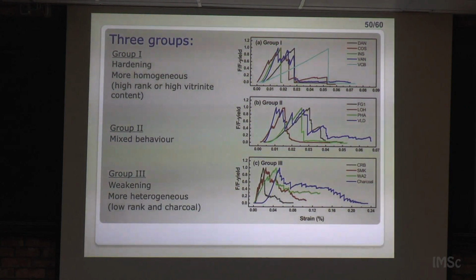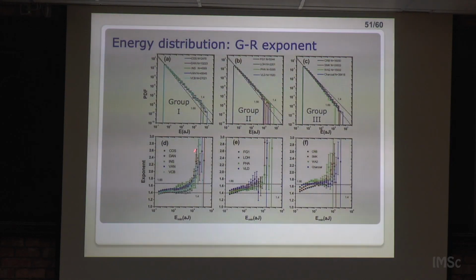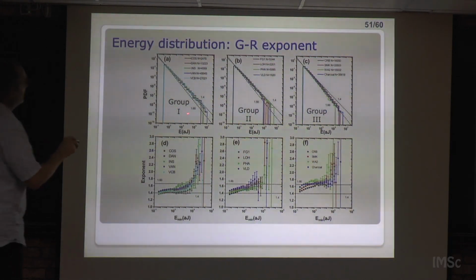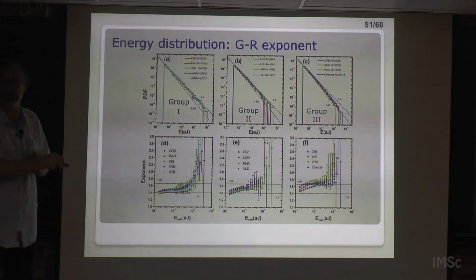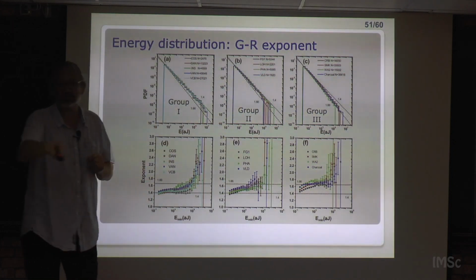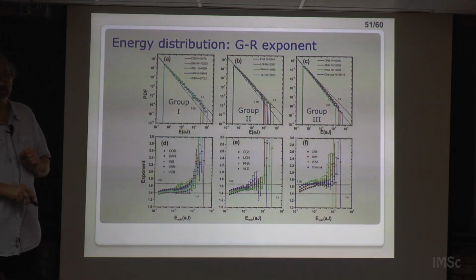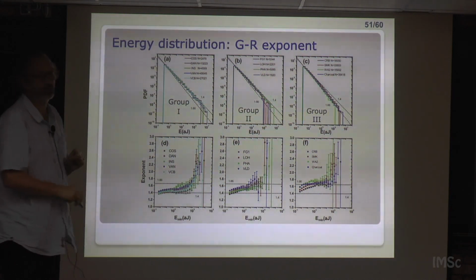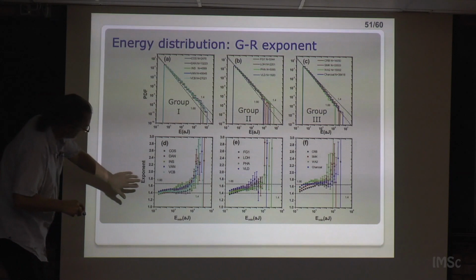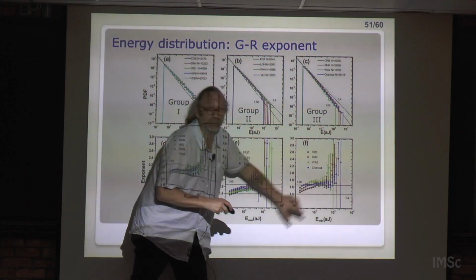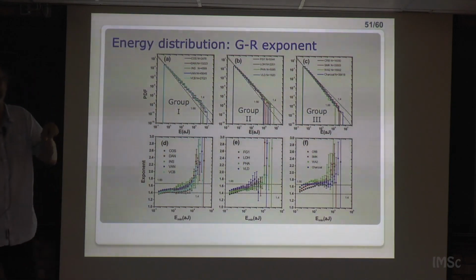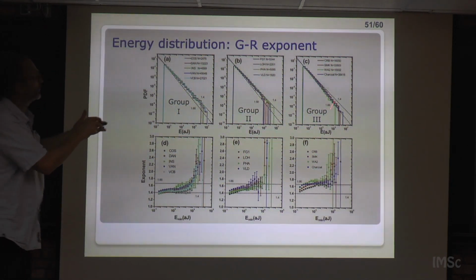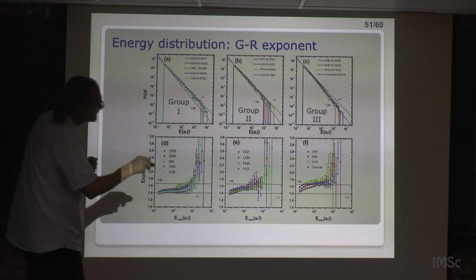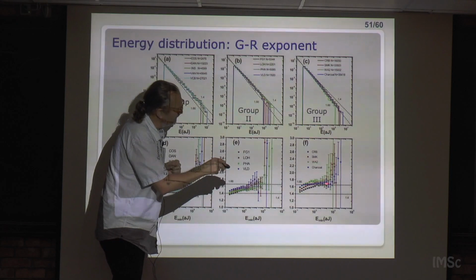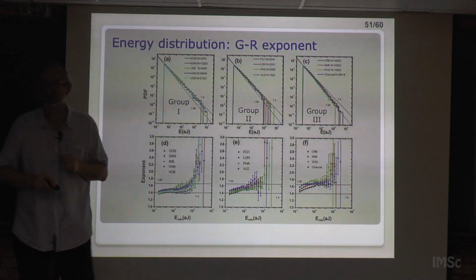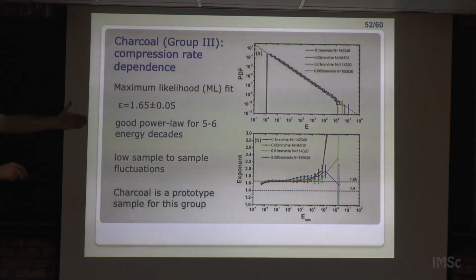And then we do the analysis of the two groups, and we compare. What do we find? The Gutenberg-Richter exponent, maybe you cannot see it here, but forget group 2. For group 1 it is 1.4. For group 3 it is 1.66, the earthquake exponent. For group 3, the heterogeneous samples, the Gutenberg-Richter exponent is 1.66. You see here, these are 1.4. This is much higher, 1.6. In particular charcoal, which is what we call the prototype sample exhibiting this weakening behavior in group 3, is rather flat. It's the blue data. It's rather flat for several decades.